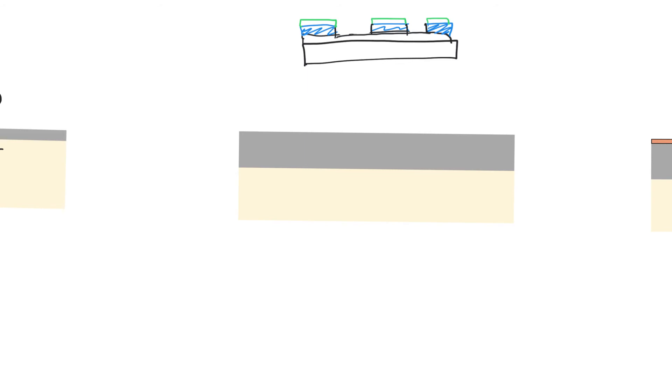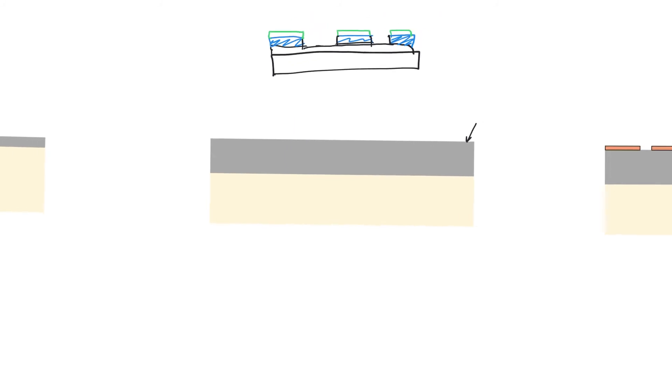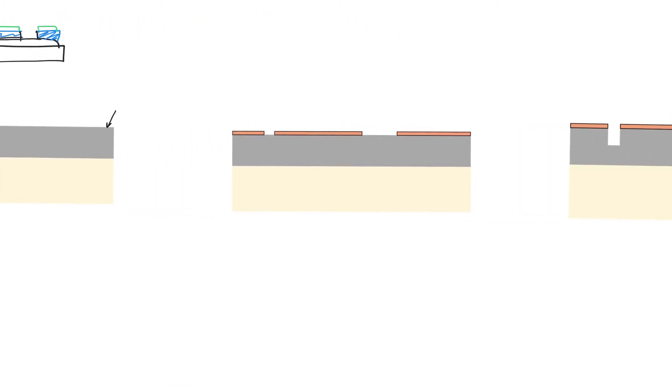And in fact, it's a process very similar to that used for trench isolation, which is why I included it in the same video. And it's very dependent on chemical mechanical polishing, as we will see. So we begin with a chip in which there's a layer of silicon dioxide and it has to be perfectly flat. So we have to use CMP to flatten it first. Then we apply a photoresist and expose it and develop it. The areas that are exposed from the photoresist that will be developed away are the areas where we actually want the copper wires.